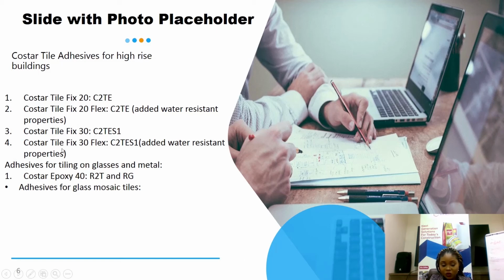So you have your regular Tile Fix 30 bag, 20 kg bag, and then you have a mixing liquid that you'd use in mixing it. And the liquid is actually an acrylic binder. So instead of mixing with water, you're mixing with the binding agent. So you can imagine the tensile strength you'll be achieving with the Tile Fix 30 Flex.